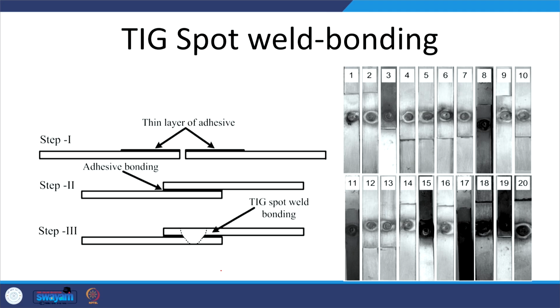Okay. Now, this kind of hybridization can also be done through TIG welding. In that case, two sheets are there, we apply adhesive, then they are placed in overlapping conditions with the adhesive, and then heat is applied on the top sheet by controlling a suitable arc, welding current and voltage. So, here melting of the top sheet and part of the melting of the bottom sheet is realized, and this in turn helps in development of the metallurgical joint, with other areas where the adhesive joint will be contributing. So, this is how the TIG spot weld bond is developed, and we get the appearance of the TIG spot weld joint of this kind.